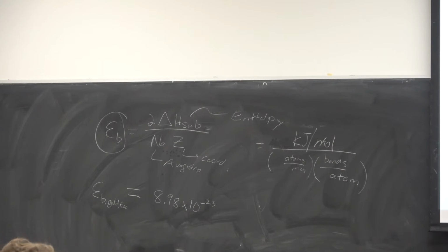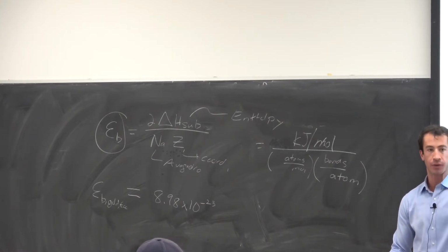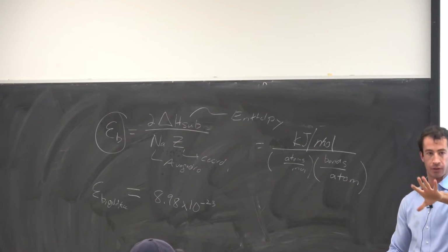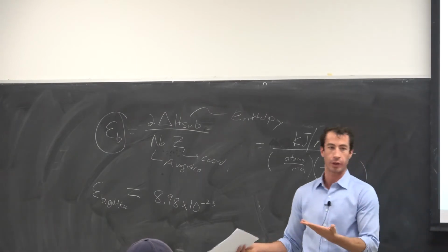It will matter if you get to smaller and smaller systems. Yeah, definitely. But for these kinds of molar quantities, you can ignore those. Yeah. So if we were talking about something on the order of a very small quantum dot, then it might start getting that. Totally. And in her example, she goes through a gold 13 cluster, gold 55 cluster, gold 155 cluster, and the energy starts to approximate bulk gold as you get bigger and bigger.